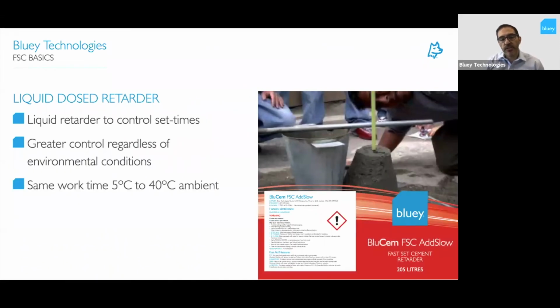One of the biggest changes we've made though to the product is the liquid dosed retarder. So the product has always been retarded using a powder retarding agent, which was added at the factory. Problem with that is once it's added at the factory, it didn't matter whether you had a 40-degree day or a 5-degree day, which honestly can happen in Melbourne, just wait for it to change. You were stuck with that powder that was delivered. You had no control over it.